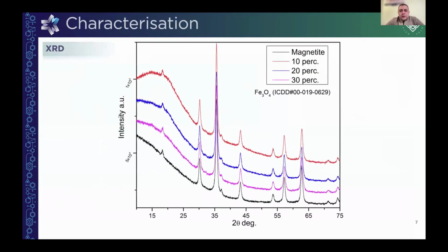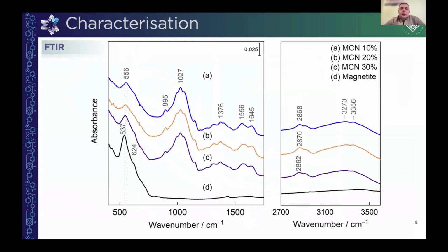So after that, we also recorded the X-ray diffraction pattern, which indicated that we got a really good connection of magnetite, because all main peaks of magnetite occurred in all 3 synthesized sorbents, 10, 20, and 30% magnetic chitosan, and they were detected by the program as really being magnetite, indicated by that score. Also, FTIR spectra were recorded, and we can see that the connection of magnetite was to amino and OH groups. So the main difference after the synthesis is that a peak at 537 wavenumbers appeared in the chitosan FTIR spectra.